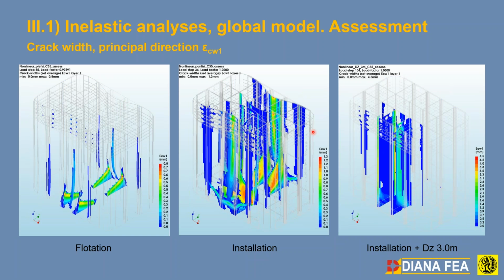How is the crack pattern? Now, the principal crack width in millimeters out of this analysis. In the flotation case, we don't exceed 1 millimeter in the base of these two walls, the interior partitions, out of the cantilever. Of course, in the installation, these cracks go up to about 1 millimeter. And then if we do the accidental, the cracks are actually different. They are no longer in the beam base, in the fixity base, but they are actually more important. That's why they cover, if you like, the colors in the contour plot, but they are actually in the sides of these walls.